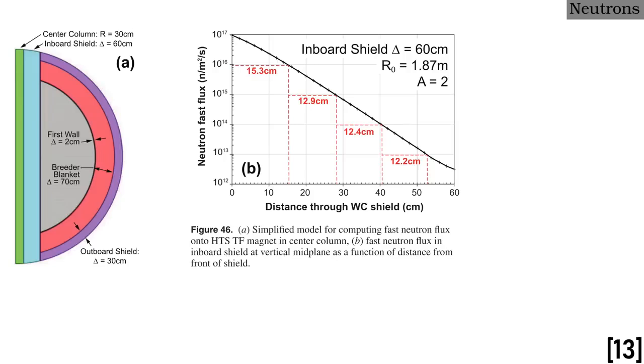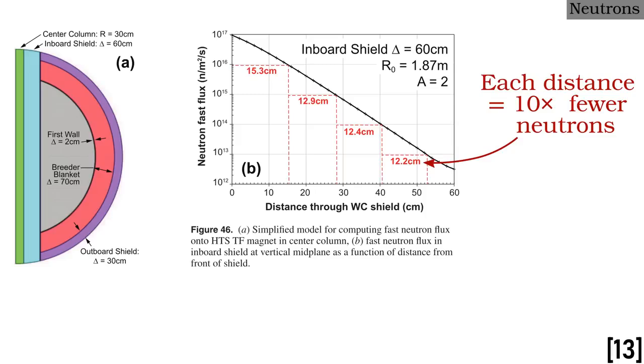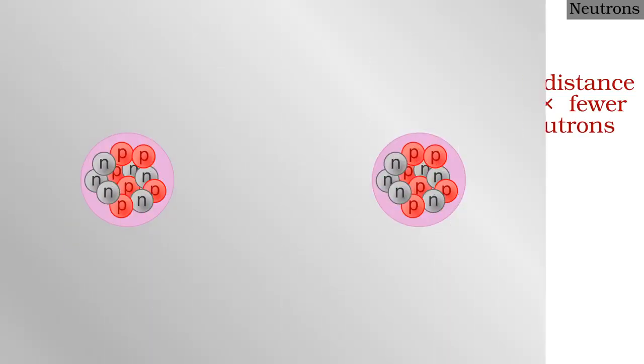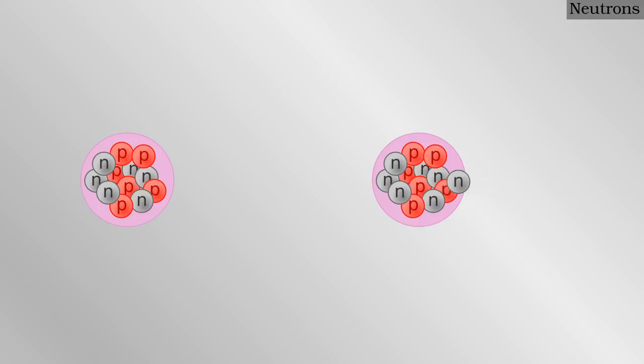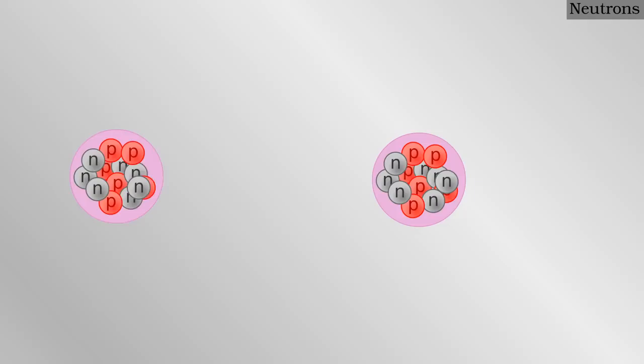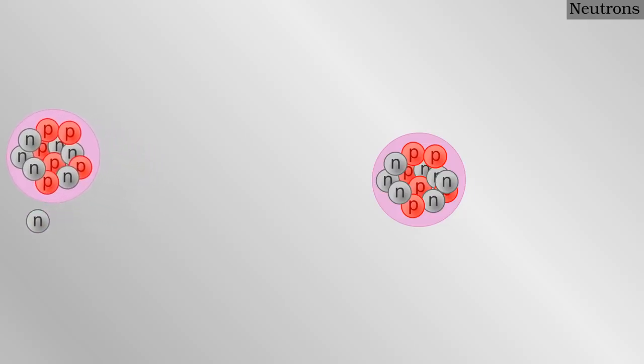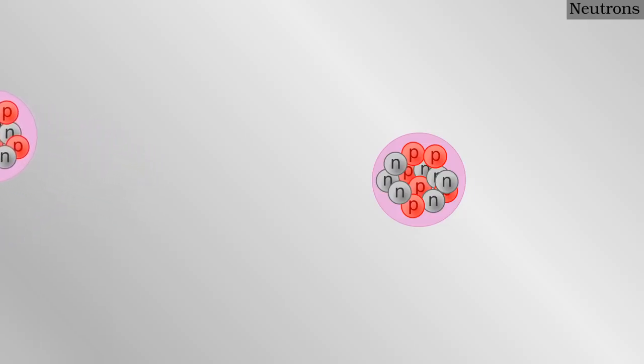For example, in my favorite paper from Princeton, they have calculated that shielding in a realistic power plant would reduce the neutrons by a factor of 10 for about every 13.5 centimeters, meaning a factor of 100 for 27 centimeters and so on. If the absorbing material had a higher neutron absorption cross-section, this thickness would be smaller and vice versa. There are 2 important results of neutron interactions. Firstly, the neutron may be absorbed into the target nucleus, which fundamentally changes it, possibly into another element. Secondly, the neutron may transfer an enormous amount of energy to the nucleus, causing it to be displaced. In the latter case, the neutron may be absorbed, but may also continue moving independently and strike other nuclei later.